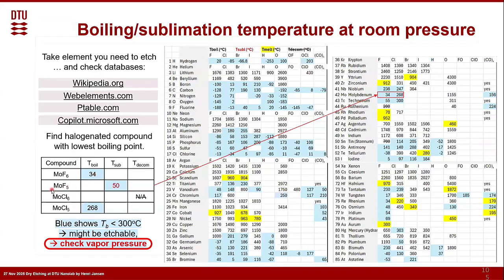For molybdenum pentafluoride, I see that it sublimates at 50 degrees. And for instance, for molybdenum hexachloride, it says it will decompose. Decompose means it goes down to a lower halogenated species or compound like MoCl2.